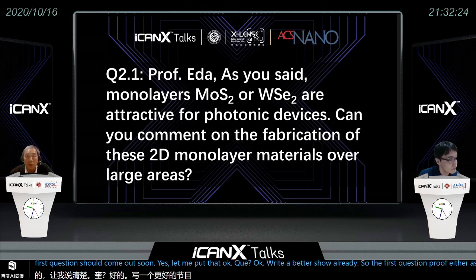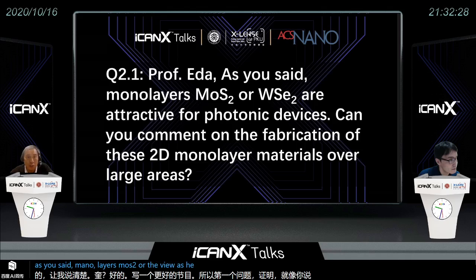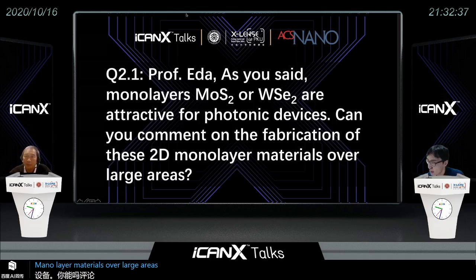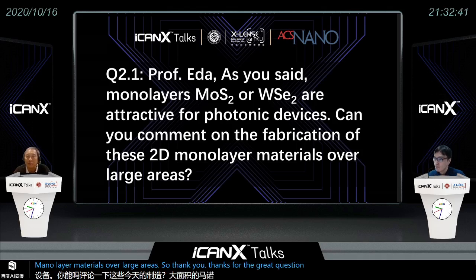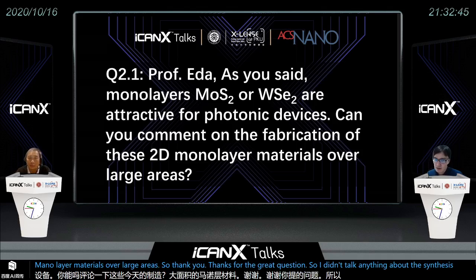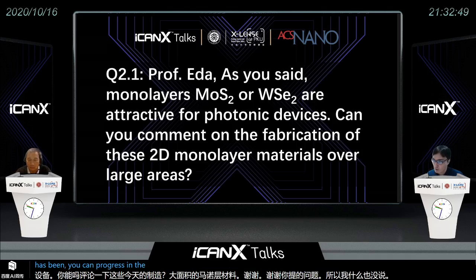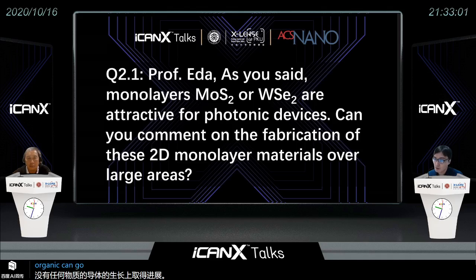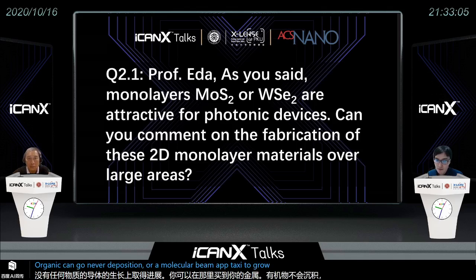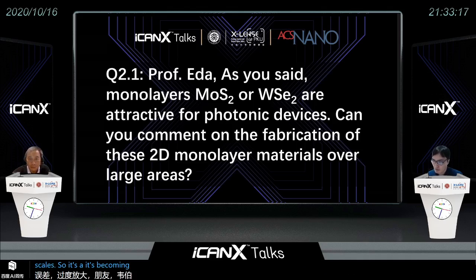So the first question, Prof. Eda, as you said, monolayers MoS2 or WSe2 are attractive for photonic devices. Can you comment on the fabrication of these 2D monolayer materials over large areas? Yeah, so thanks for the great question. I didn't talk about the synthesis, but there's been significant progress in the growth of monolayer semiconductors, and you can apply either metal organic chemical vapor deposition or molecular beam epitaxy to grow fairly high quality monolayers over 4-inch wafer scales. So it's becoming quite mature technologies, I would say.